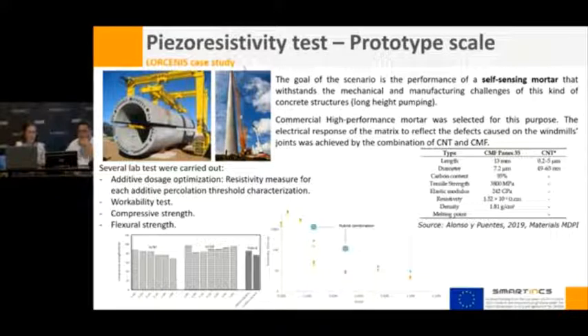It has several different concrete segments. In all of them, the mortar in the joints is pumped from the top, but the last one, the highest, is manufactured horizontally, and then when it is hardened, it is put on top of the tower. So the mechanical challenge there, and also the manufacturing one, is that pumpability is really important in this kind of structures.